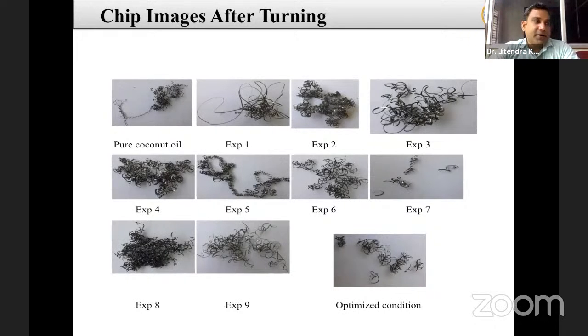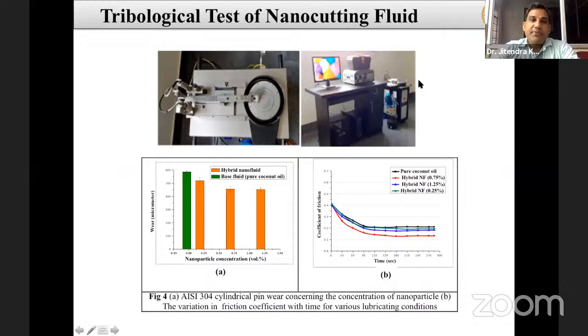In that case, we perform the test of the nano cutting fluid on the pin on disk setup. Here we use the 0.75 concentration of cutting fluid, 1.25, all the cutting fluids, and we observe the coefficient of friction with respect to time. We observe that it is almost the same, but in the case of the 0.75% concentration, it gives the lowest coefficient of friction.